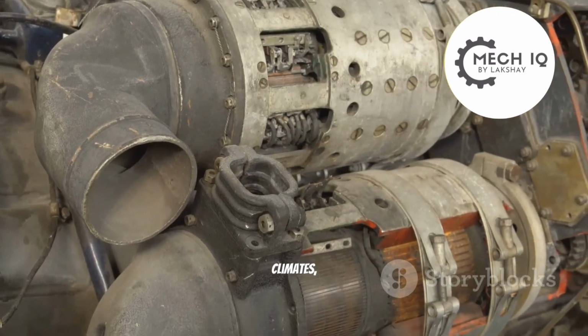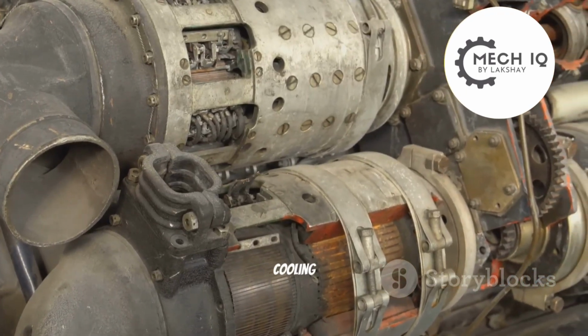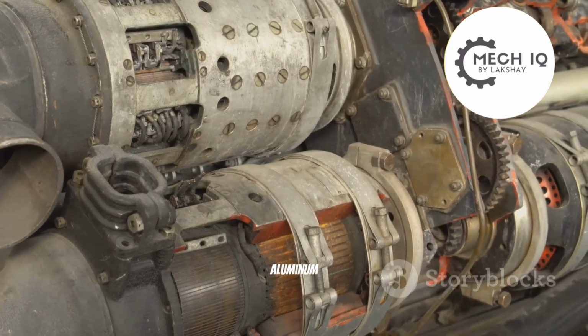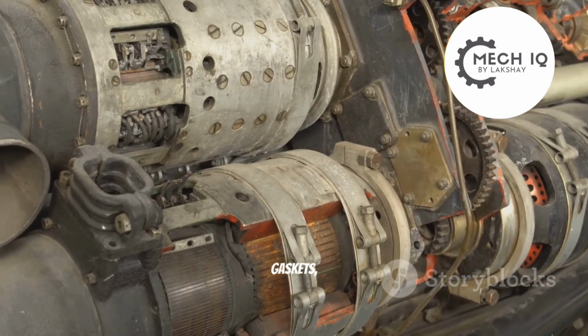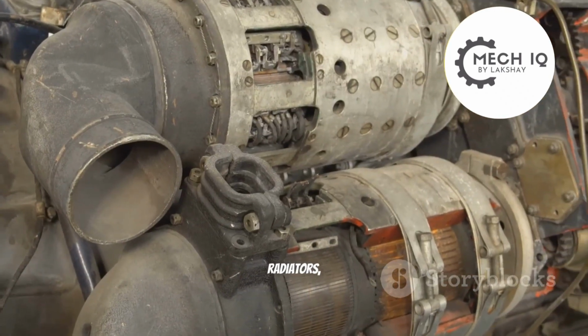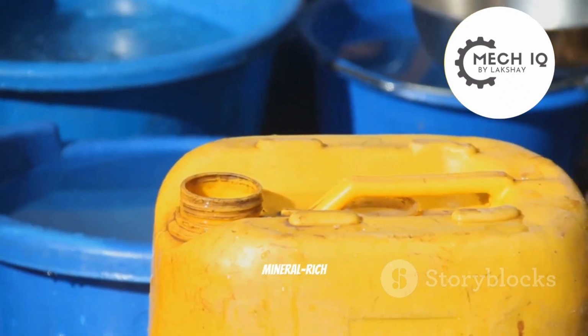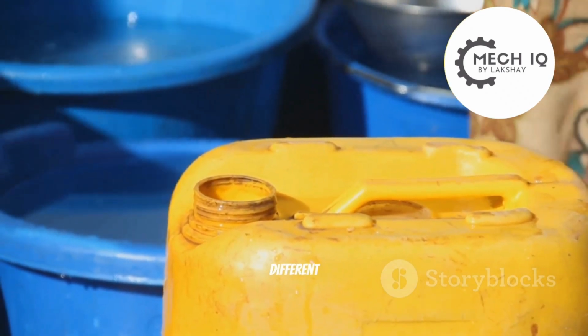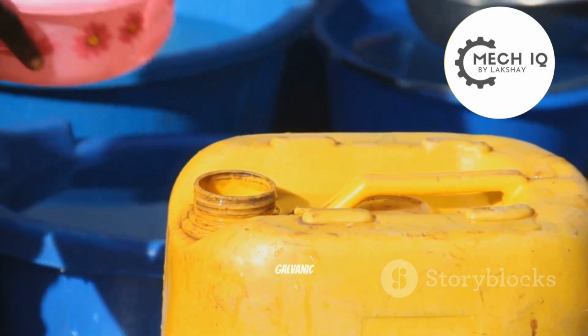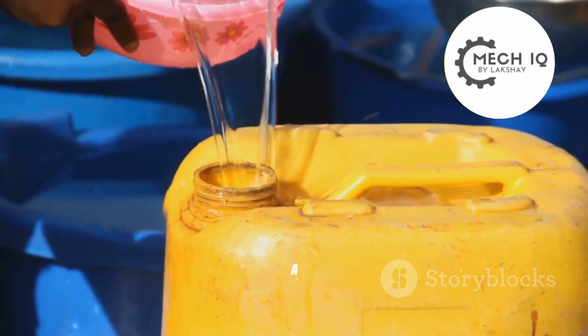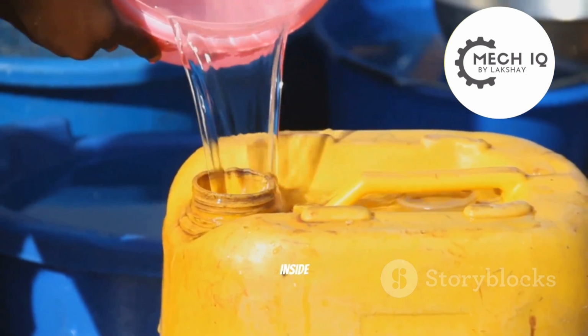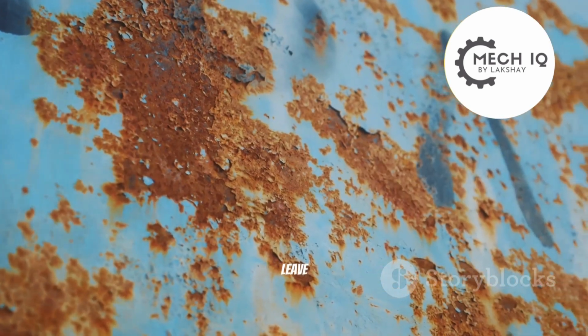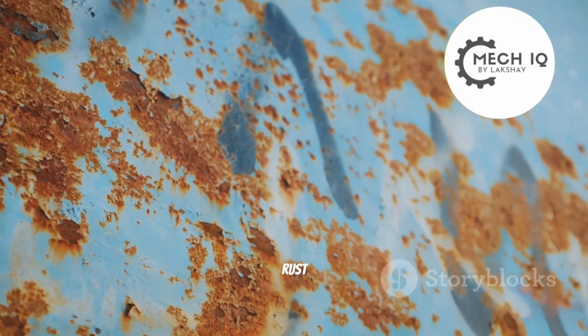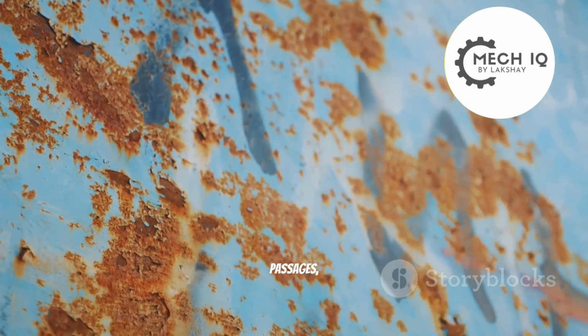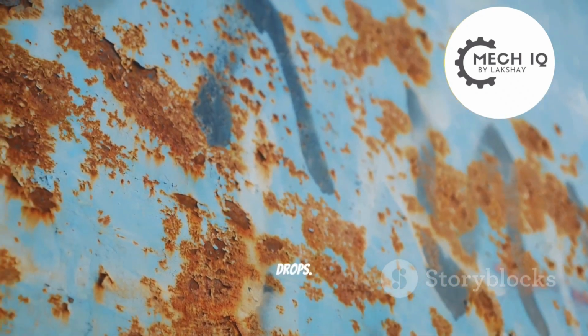Even in mild climates, water is a bad idea. Your cooling system mixes metals: aluminum heads, cast iron blocks, steel gaskets, copper or brass radiators, and water pump parts. Plain mineral-rich water is an electrolyte. Two different metals plus an electrolyte equals galvanic corrosion, a low-power battery inside your engine. Electrons leave reactive aluminum for iron or copper. Aluminum pits, rust and scale clog passages, impellers wear, flow drops.